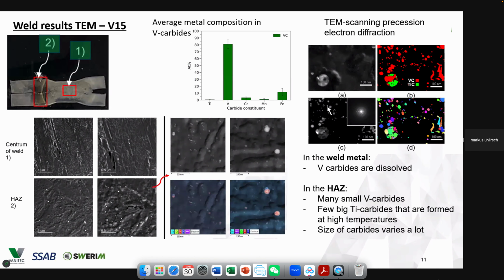Here we can see the TEM results for the 0.15 weight% material. For this material, TEM analysis was done in the weld and in the heat affected zone. You can see the areas marked in the top left optical microscope image. For those tests, it was seen that in the weld, the carbides were pretty much dissolved, but in the heat affected zone there are quite a few small vanadium carbides and a few bigger titanium carbides. So it can be said that the size of the carbides varied quite a lot.